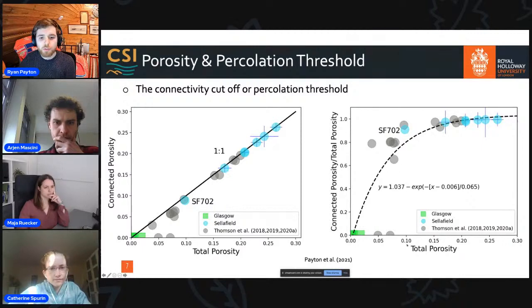So this 10% value is super crucial, because if we can analyze rocks and say, okay, there's 10% total porosity, and we decide that that is our percolation threshold, then anything above that should be able to provide a good level of connectivity, which is a desirable characteristic of a potential storage reservoir.